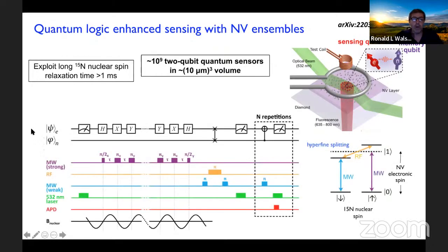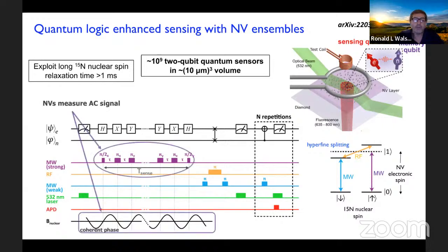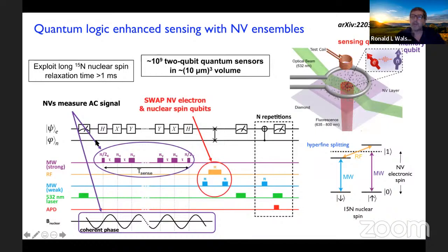This shows the quantum logic that we undergo. I outlined it previously for the single NV experiment using single proteins. It's a similar idea here, but we've altered it and adjusted it to make it work for ensembles. We first measure the AC signal that would be coming from the NMR sample, or in the test case from a signal coming from an antenna that we're using as a test signal. Then we swap, once that information has been measured by the NV and it's an accumulated phase on the electronic spin of the NV. We swap that information with a swap gate onto the nuclear spin.